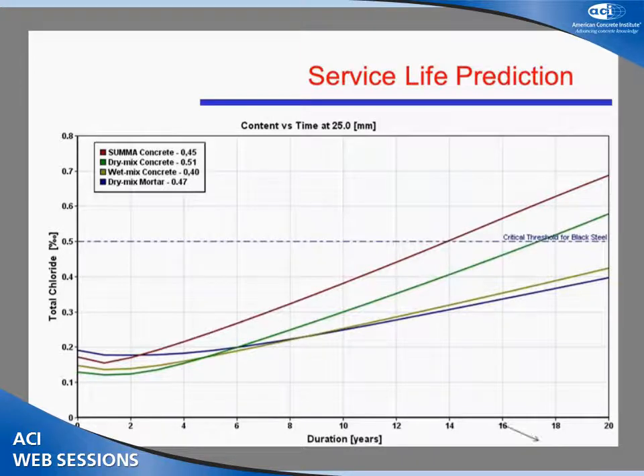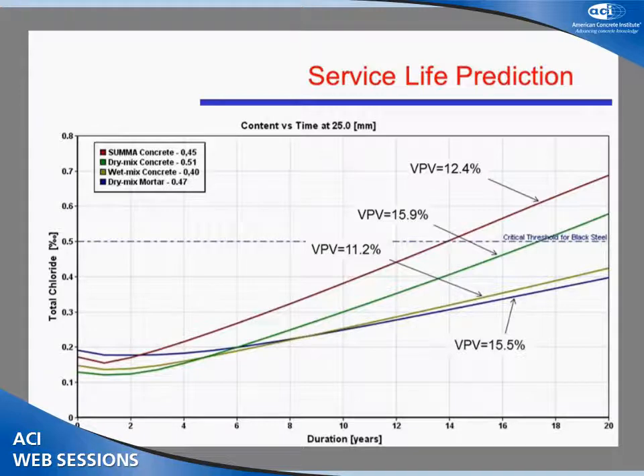Now, let's do something interesting. Let's compare that to the volume of permeable voids, which was measured using ASTM C642. What you have essentially is that it doesn't correlate with the volume of permeable voids. If you were to base your choice of mixture design on ASTM C642, specifically the volume of permeable voids, you would have chosen either the wet mix concrete or the SUMMA concrete. Now, according to this, the SUMMA concrete would be the first one to go. Another thing is that there's quite a difference between 11% and 15%. For those who have tested and used ASTM C642, 4% is quite a difference.